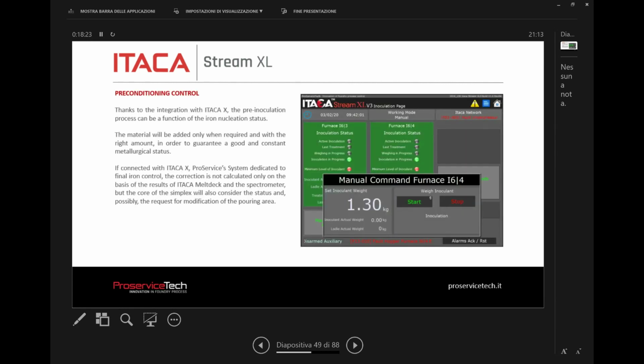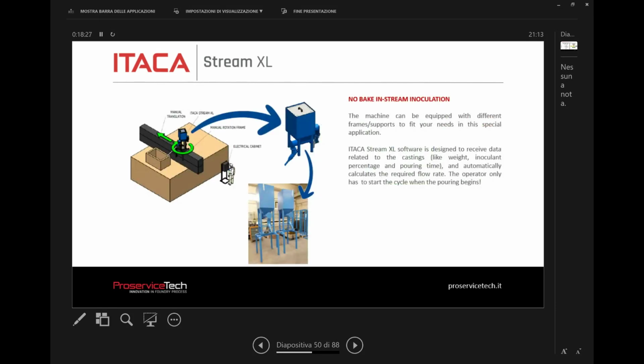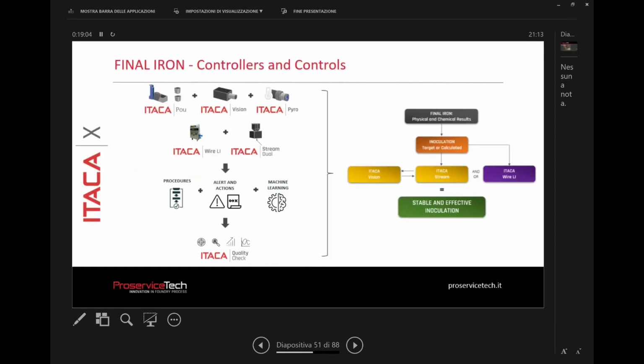The ITACA Stream XL is also used a lot for this application, for big molds. We put the stream inoculation device on top of the mold. We have sold this to Caterpillar and, for example, Shrem in Poland. So there are systems that you can put on top of the molds, and you can use as a stream inoculation device for big castings. It can be controlled with a radio control, so you can define the flow rate, how much inoculant you want inside, and you can also pre-charge a pouring curve in this machine. So final iron. Also in this specific field, we have some customers in the UK, like URAC, for example, that use these systems.